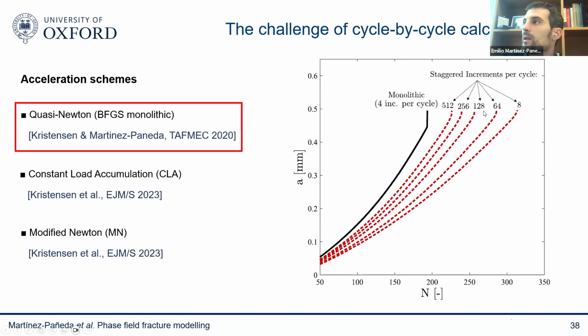And we have shown that in a very first paper. We did fatigue, and we showed that with a monolithic quasi-Newton approach, we can solve the problem with 4 increments per cycle. You can also do that with a single pass scheme, but you need to use a lot of increments per cycle, not even 500 to get the right result. So it becomes prohibitively expensive to run fatigue simulations with single pass standard schemes.